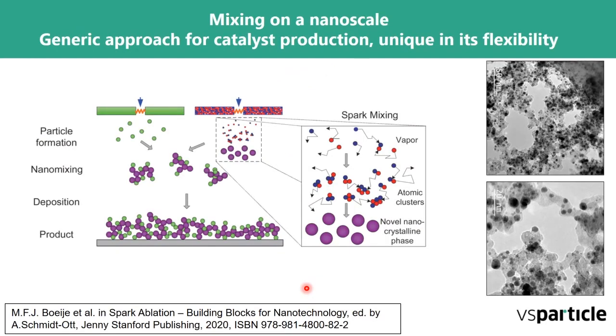So this was about atomic mixing. But what you can, of course, very easily do in an aerosol is mix particles coming from different sparks, consisting of different materials, and then they will coagulate in the aerosol and form particles that are mixed on a nanoscale. Then you can deposit these particles onto a substrate, or you can co-deposit the particles coming from two different sparks on the same substrate.